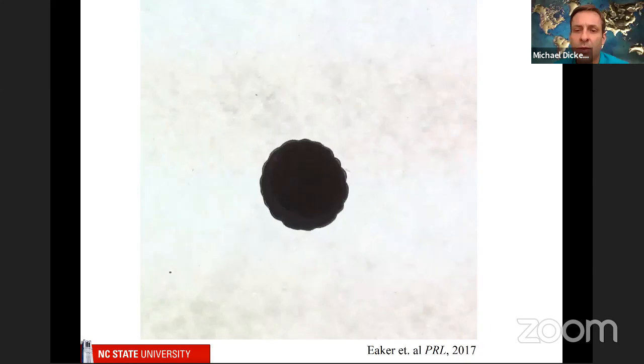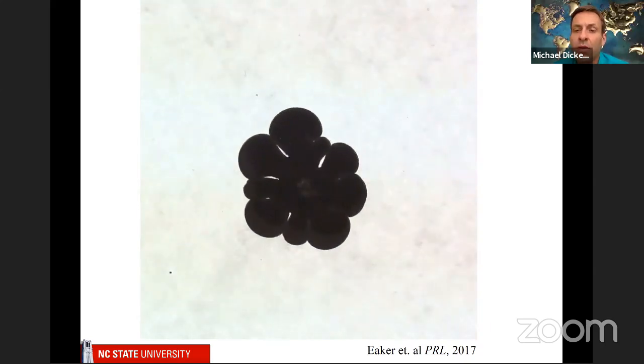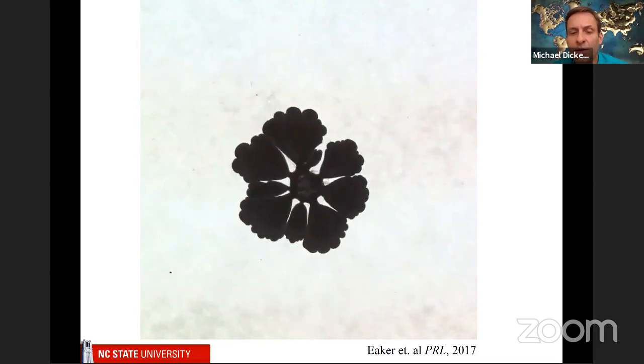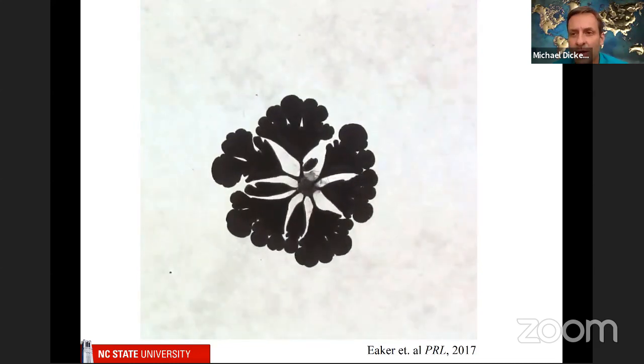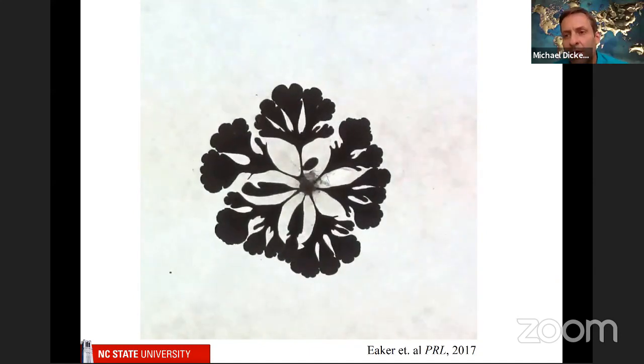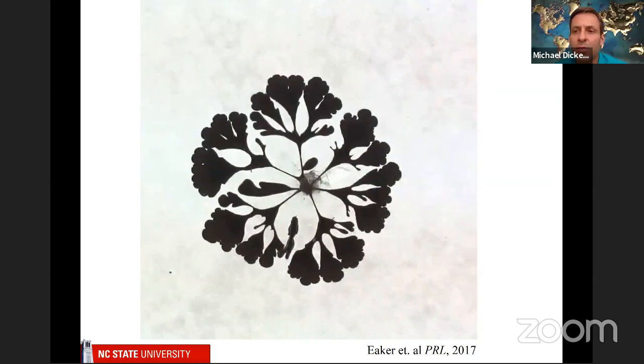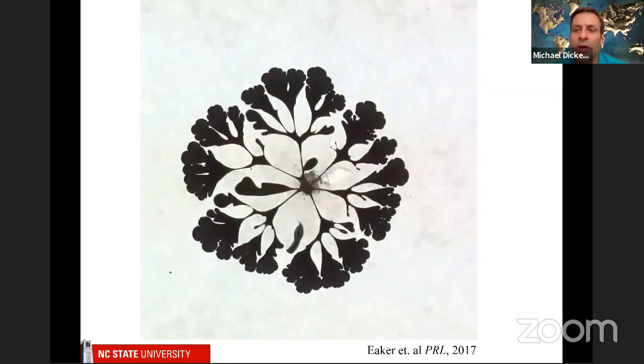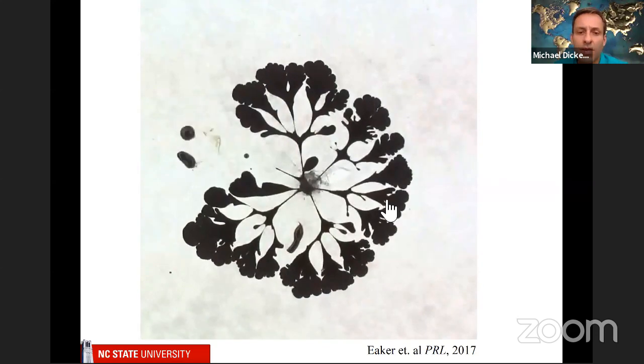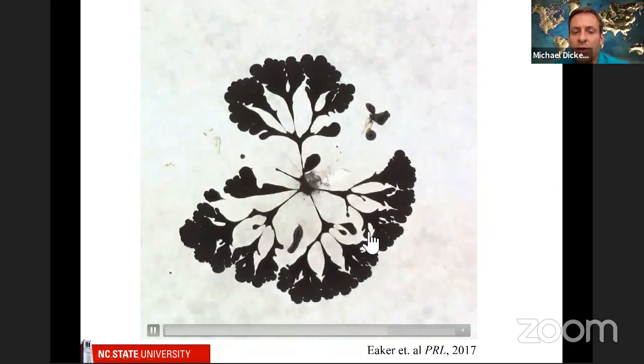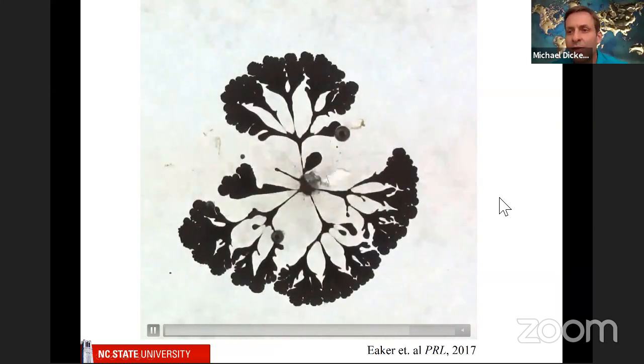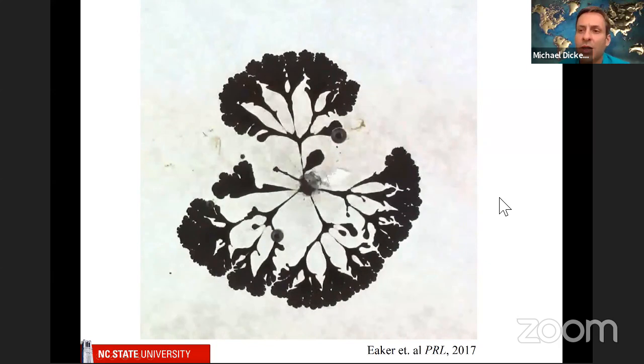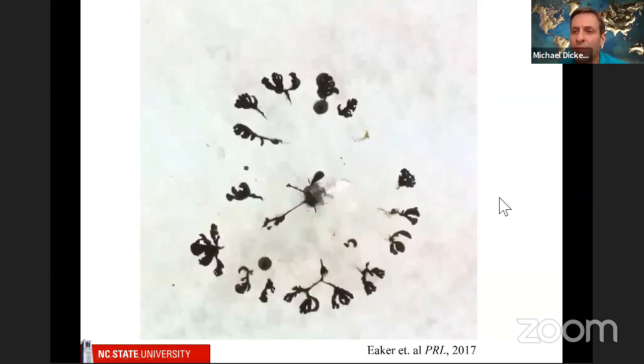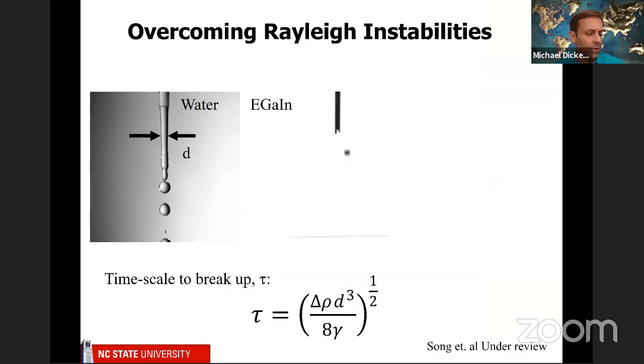This is looking top down on the liquid metal. We're applying 1 volt to it. And you'll see that it starts spreading due to gravity. So gravity is squishing it into the screen. But not only does it spread, it starts forming fractals. These are very likely due to Marangoni type instabilities. But the point is that the metal spreads and increases in area in a way that doesn't seem bound. The only way it breaks up is if these small little threads break up. And once it breaks up, the oxide dissolves away and it beads up. So it's really the oxide that's doing the magic here. It's, again, not electrocapillarity, not electrowetting. This is due to electrochemistry at the interface. So I guess this is my last result slide.